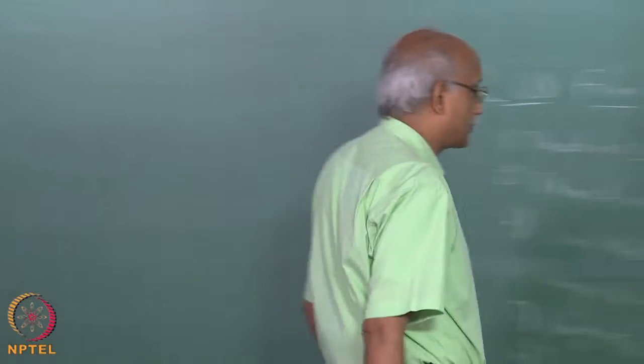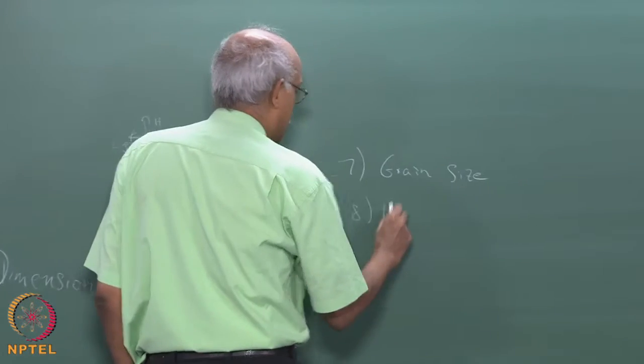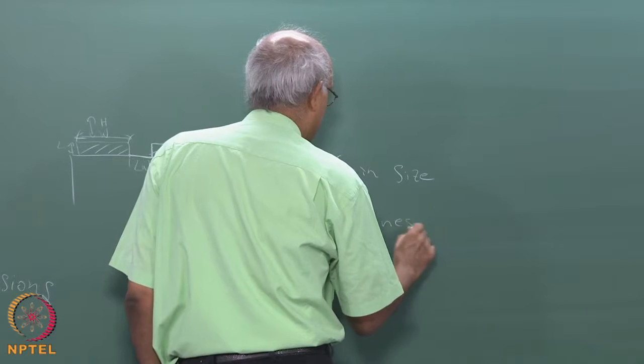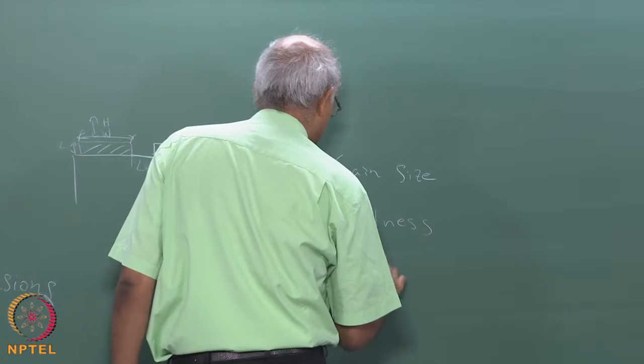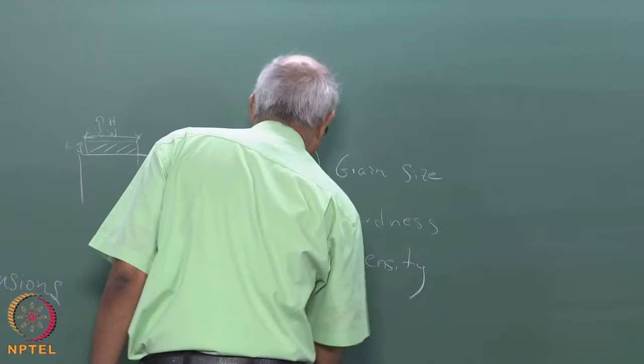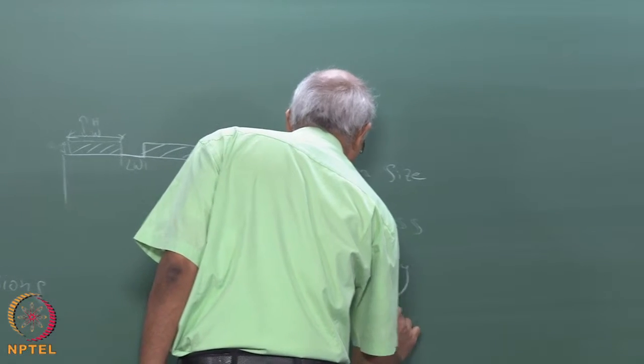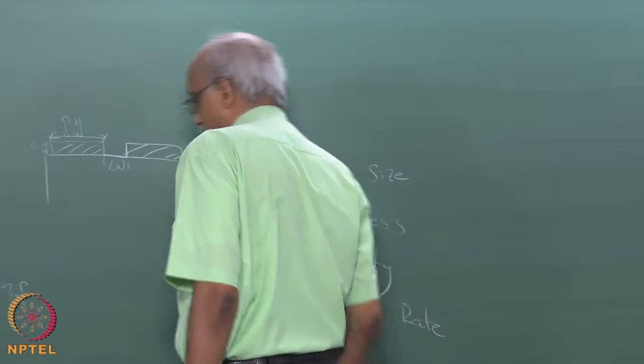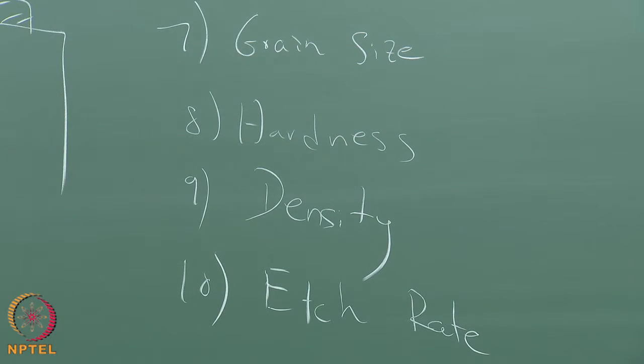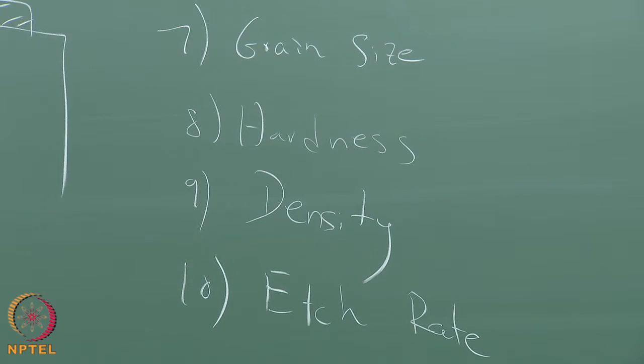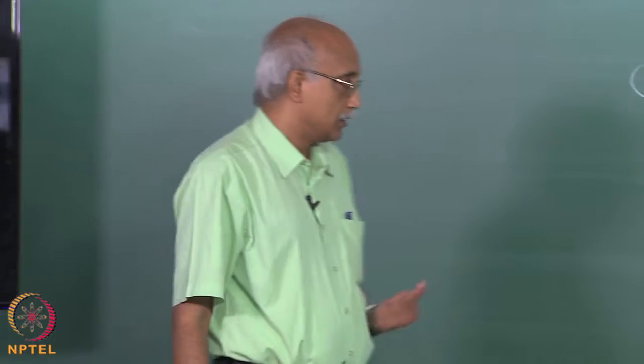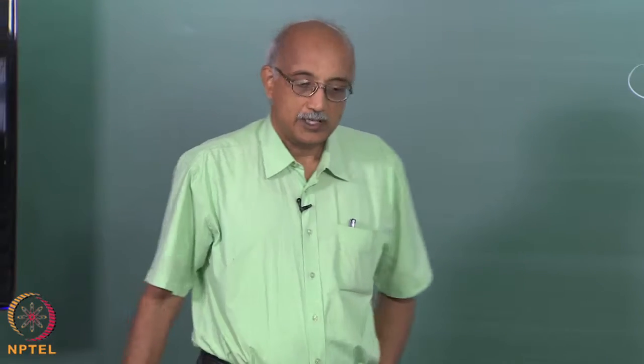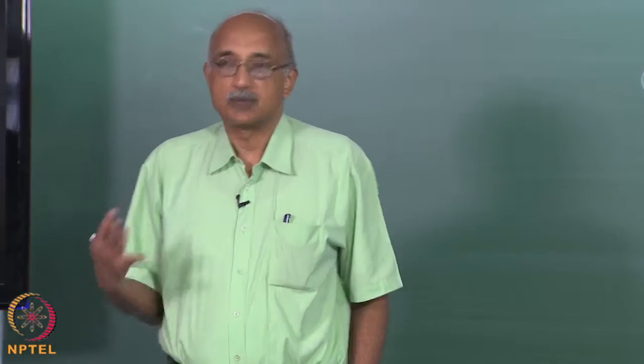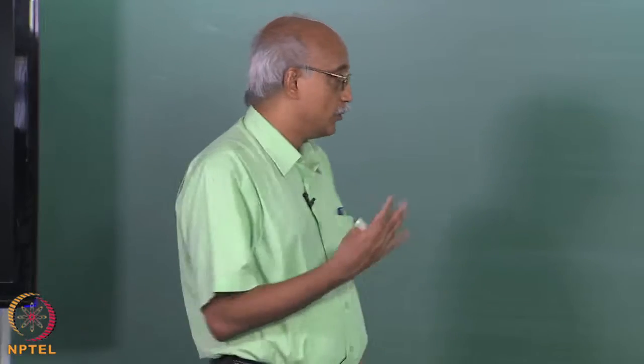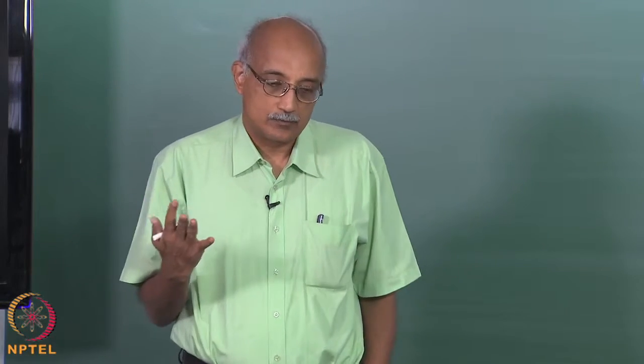What else? We certainly have to look at properties like hardness, density, and another property that we had mentioned earlier, etch rate, which is a good measure of how sustainable the CVD film is under aggressive environments. So, there is obviously a fairly long list of things that you can measure about a CVD film, and where you stop really depends on, again, your process requirements and your customer requirements.